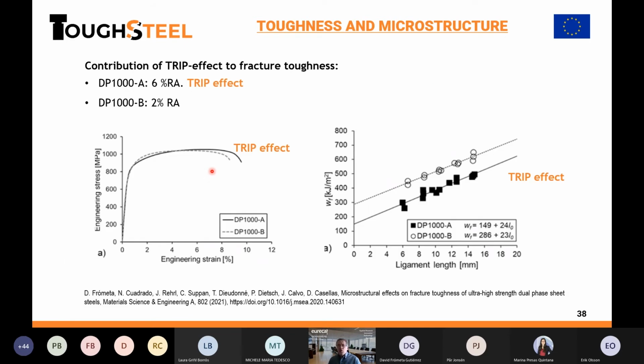Another example is if we want to assess the contribution of the TRIP effect, the transformation-induced plasticity, in fracture toughness. You can find more information in the papers you see in the slides. In this case, we compare two materials, named A and B. Both are third generation high strength steels, and one has a TRIP effect. If you look at the conventional global formability, the TRIP effect contributes to better ductility. But if you look at the essential work of fracture, remember, the work of fracture at ligament length interception is the fracture toughness, the one having TRIP effect has lower toughness. So the TRIP effect improves global formability, as is well known, but does not improve the fracture toughness. On the contrary, it reduces it.